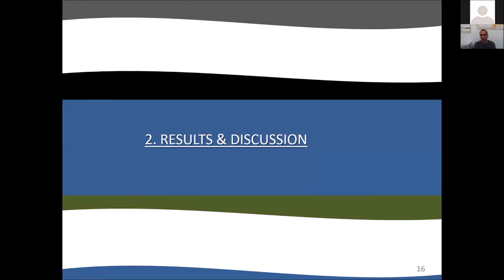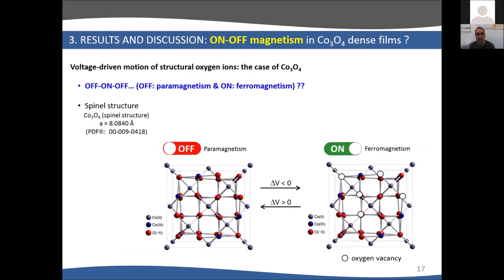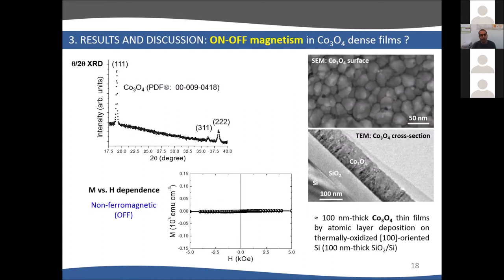What we have done in our group in the last few years is what we call on-off magnetic transition. We first studied metallic porous layers and saw that when there were oxides, the effect was larger. So we went directly to cobalt oxide, which is paramagnetic at room temperature. It has this spinel structure. By applying a negative voltage, we could transform this paramagnetic state to ferromagnetic state. We ascribe this to the generation of oxygen vacancies. You have locally some exchange coupling between cobalt atoms, generating ferromagnetism. This could be reversed by applying positive voltage. This is an on-off transition, similar to switching a lamp on or off with voltage.